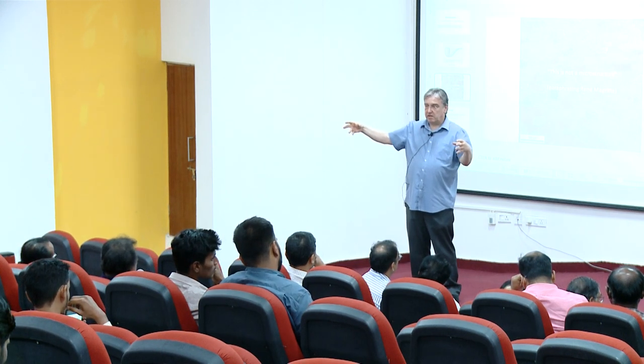It's perfectly possible on paper. In reality, it depends, of course, on how good and how deep is your understanding of the thermodynamical principles. And I think we have to say there is an important difference between equilibrium thermodynamics, where the system goes from a stable initial state to a stable final state, which can be quite well understood by thermodynamic models. But of course, in metals, very often, we deal with non-equilibrium processes. So at best you start from a stable initial state, and you do something, and you end with a state which is far out of equilibrium. So there, thermodynamics is not going to teach us the evolution laws of such a system. So that is the main roadblock.